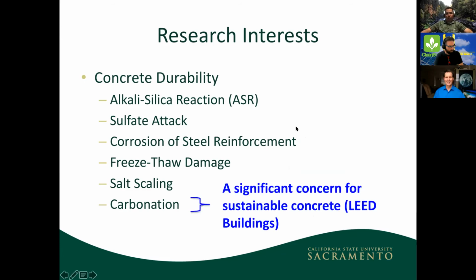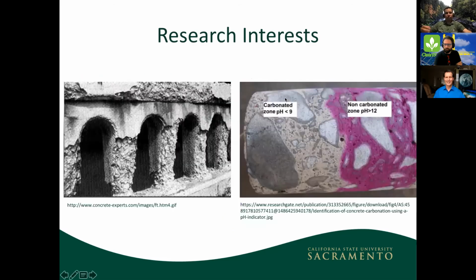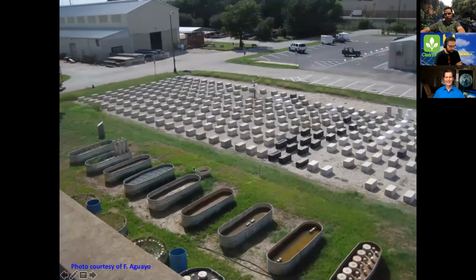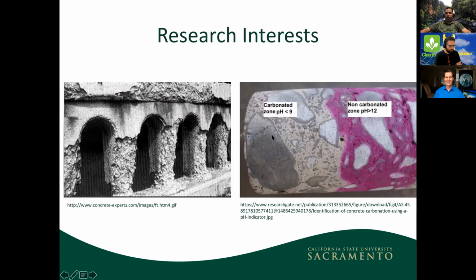So there's a lot of different things that we have to be careful of, especially as we're looking at these new materials. We have to make sure, are they still giving us a durable product? Okay, this goes back to, it doesn't matter if we're using 10% cement. If it's only going to last us 6 months, it's of no use to us. We have to make sure it's still a durable material. Okay, so the picture on the left shows the freeze-thaw damage. That's what happens when the water freezes inside of concrete. And the picture on the right shows concrete carbonation, which is a significant concern when you start driving the cement content down.